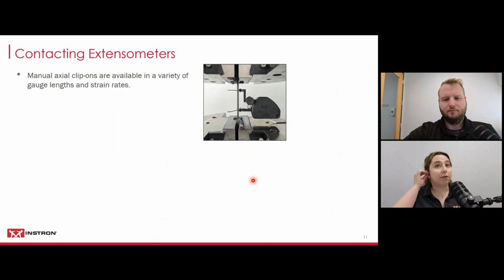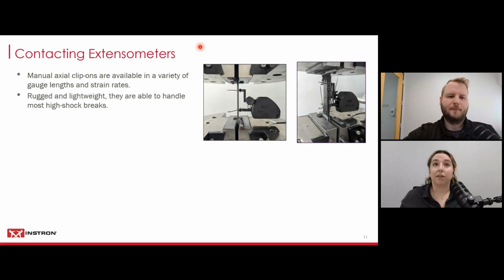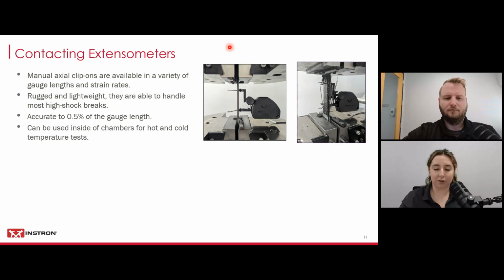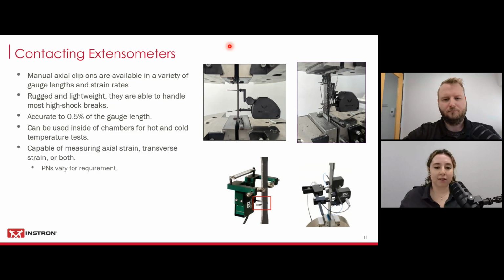So kicking it off, high level for contacting extensometers, manual axial clip-ons are available in a variety of gauge lengths and strain rates. They're typically considered rugged and lightweight and are able to handle most high shock breaks. We show an example of one remaining on in our lab. They are accurate to 0.5% of the gauge length, so your accuracy is dependent on what gauge length you're testing to. They can be used inside of chambers for hot and cold temperature testing. And they are capable of measuring axial strain, transverse strain, or both. But depending on the type of strain measurements that you want to take, your part numbers are going to vary. It's not going to be a one-size-fits-all.